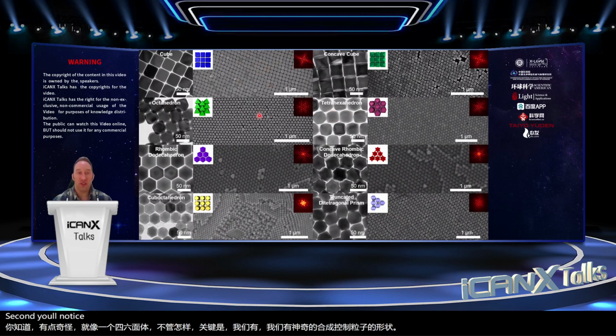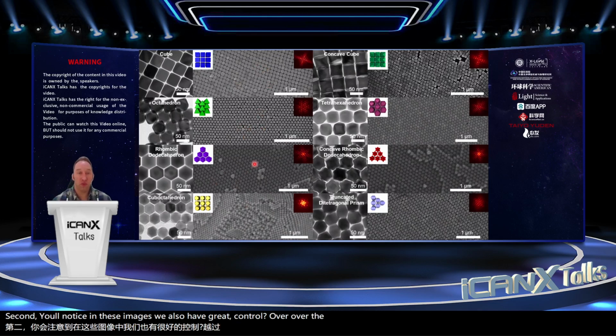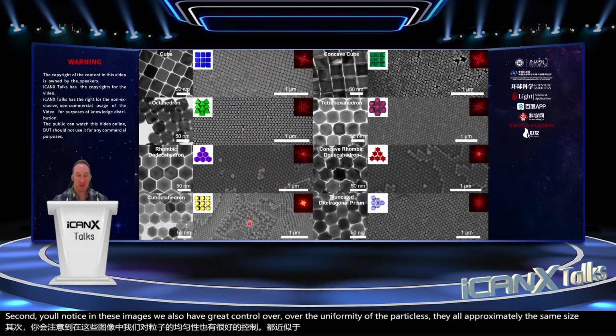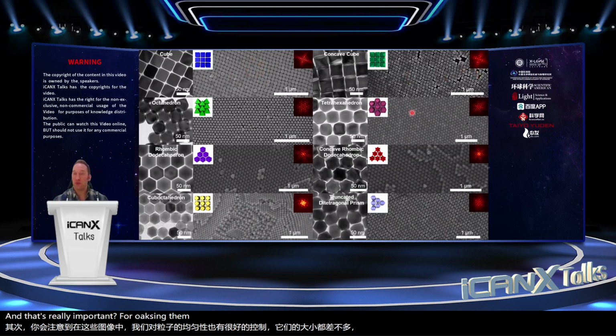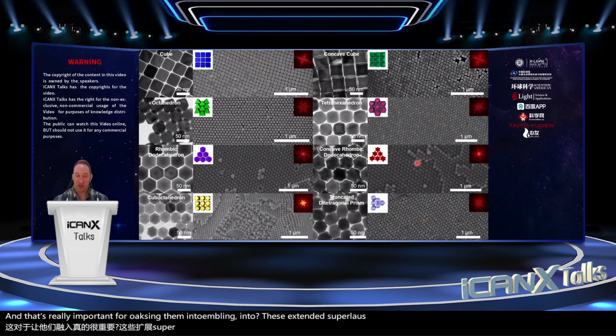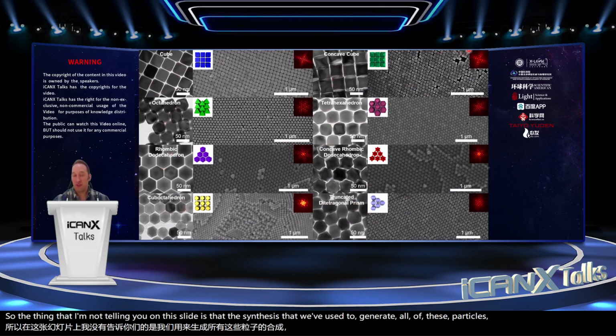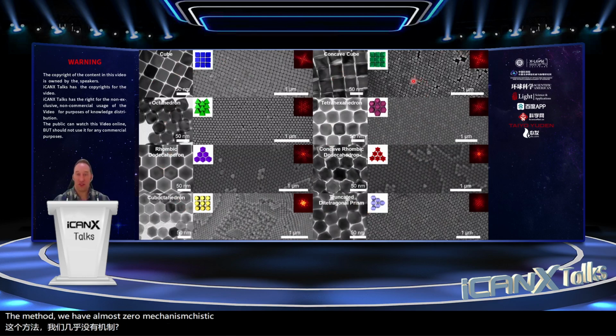Second, you'll notice in these images, we also have great control over the uniformity of the particles. They're all approximately the same size. And that's really important for coaxing them into assembling into these extended superlattice architectures. So the thing that I'm not telling you on this slide is that for the synthesis that we've used to generate all of these particles, we have almost zero mechanistic understanding of how those syntheses work. We are essentially just following a recipe that's been published in the literature that was determined empirically, and we get out these particle shapes. We have almost no idea why one synthesis generates this shape and a very similar set of conditions generates this completely different shape. And so this is obviously a major problem.